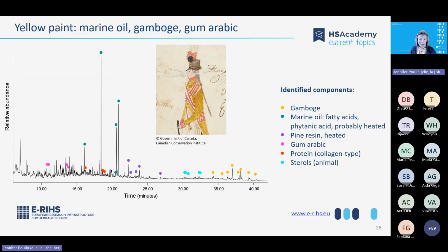In the yellow paint, I identified an oil binder, which is probably from a marine source like fish. And the presence of alkylphenyl alkanoate compounds seems to indicate that the oil has undergone some degree of heating, which isn't unusual if the oil was rendered from a marine animal source. The yellow pigment is gamboge. We see some heated pine resin and sterols.